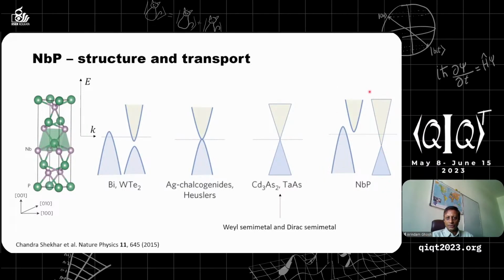This is the energy of the electron as a function of momentum, and you have these linear bands at the Fermi energy. You can compare or look at the difference between that and conventional semiconductors. You can see semiconductors have a parabolic band like this. Whereas in the other case of Dirac semimetals, like cadmium arsenide or tantalum arsenide, or graphene, which I'm going to come to in a few slides, you have this kind of linear band structure.